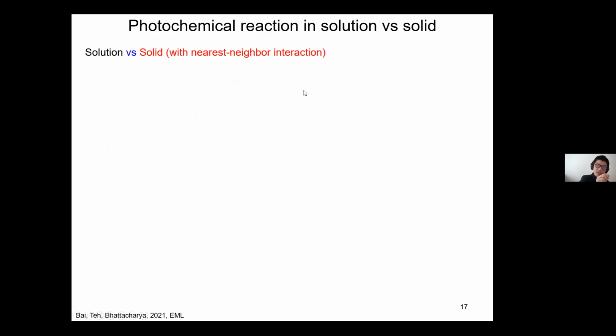So let's first look at a very simple case, solution versus a solid. So here I don't include any sophisticated elasticity, okay, or mechanics. I'm basically only considering the nearest neighbor interaction, okay? So here's the result. This is the kinetics. I'm recording the ratio of cis. So initially I have no cis. So remember, trans is in the ground state. Trans is lower energy. So initially there's all trans.